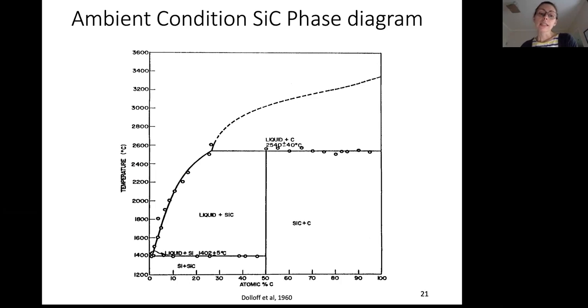But what's interesting is that it doesn't melt from silicon carbide solid straight to silicon carbide liquid. Instead, the silicon component comes out as a liquid with solid graphite. So you get decomposition of silicon carbide at this temperature rather than going from solid to liquid with the same composition. So this is interesting, especially thinking about silicon carbide in a planet, because if it were to break down, then that would be very different for your planet's chemistry rather than just a solid silicon carbide to a liquid.